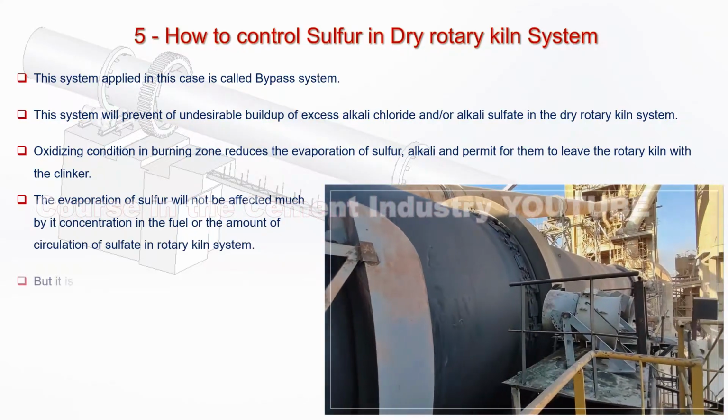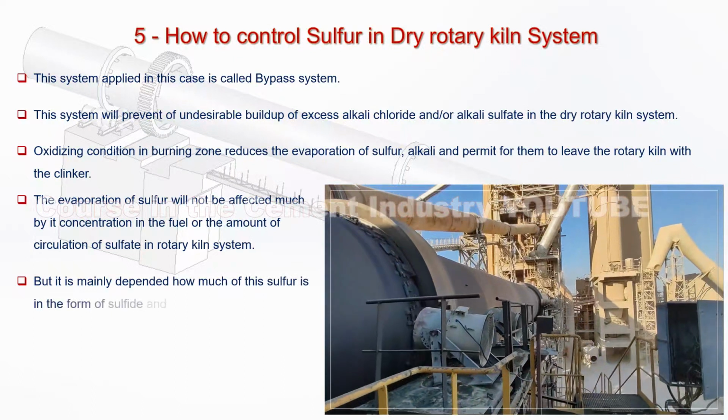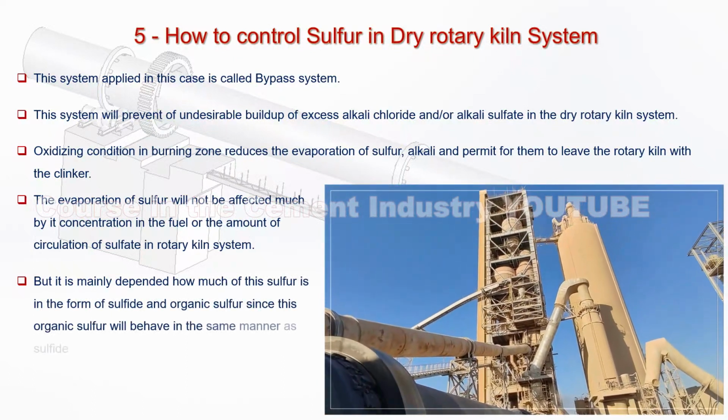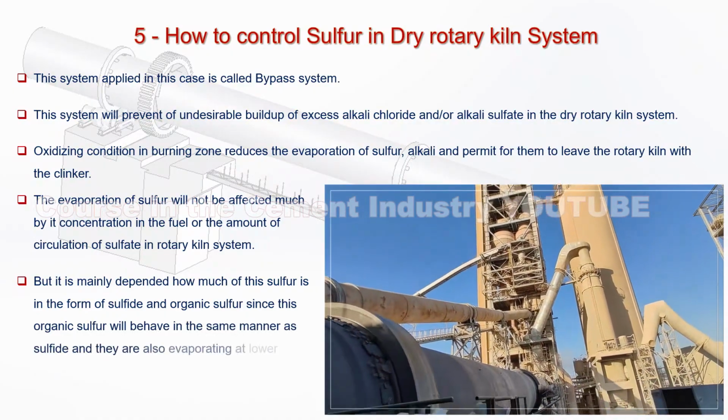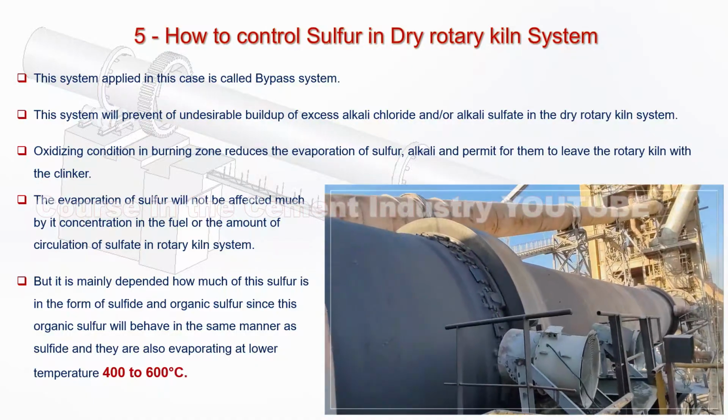10. But it is mainly dependent on how much of the sulfur is in the form of sulfide and organic sulfur, since this organic sulfur will behave in the same manner as sulfide, and they are also evaporating at lower temperature, 400 to 600 degrees C.